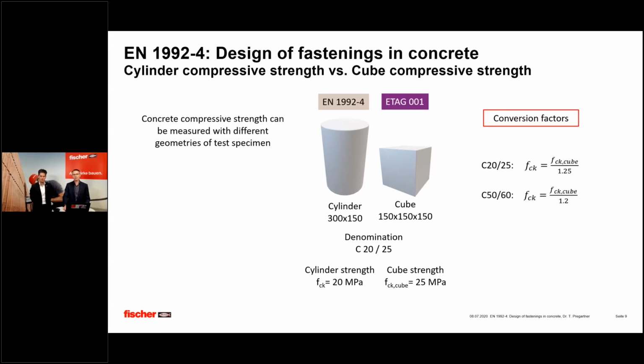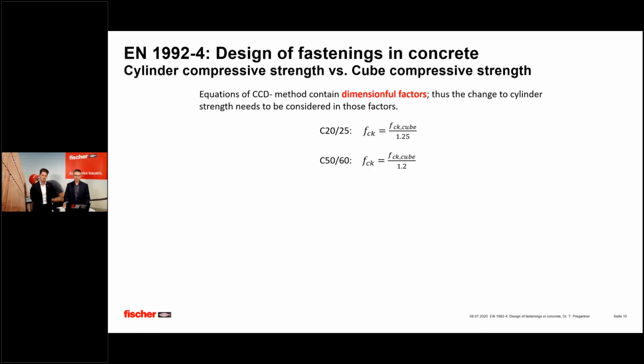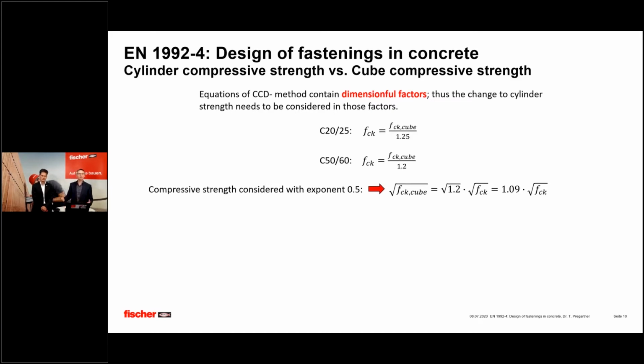Now, this difference in conversion between cylinder strength and cube strength, you have to consider in the CCD method. The CCD method has a lot of equations that contain dimensionful factors, which makes it sometimes a bit difficult, because you always have to use the same dimensions within the equation. So the first factor of it is not really clean of dimensions. Therefore, you have to consider this transfer from cube strength to cylinder strength by an additional factor. And if you insert the conversion factor of 1.2 under the square root, because the concrete compressive strength is usually considered under the square root in the equations, then you get an increasing factor of 9%.